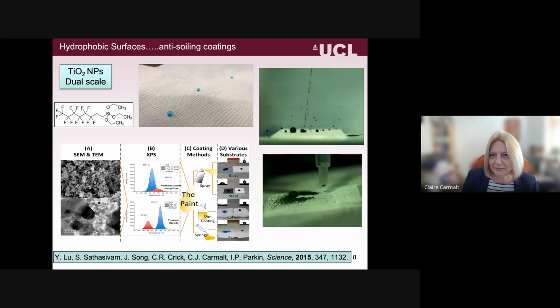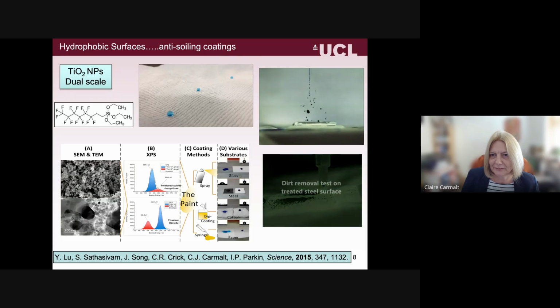And you can see in the top video that what happens is you get lots of bouncing of the water droplets due to the very hydrophobic nature of the surface. And also in the bottom video, we've put some dirt onto the surface. As the water droplet rolls, it picks up that dirt, and as it rolls, it takes the dirt away. And you can see it leaves a very pristine surface behind. So that would be a way of trying to help reduce any soiling on surfaces, whether that's in photovoltaics or in other applications such as in car wheel hubs and that sort of thing, by this rolling action.